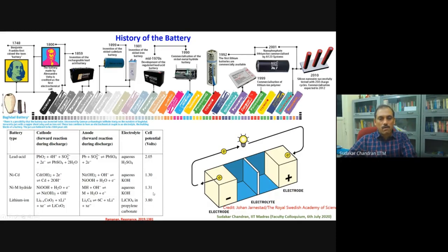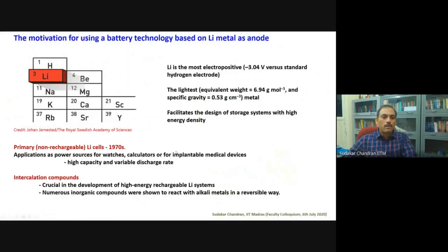But you can see a very contrasting difference. The voltage of the lithium ion batteries is almost 2 to 3 times more than any of the batteries known previously. Of course, the very use of lithium in the lithium ion battery came because it exhibits a very high capacity and also gives a very high discharge rate. This is possible because lithium is the most electropositive element we have. It's the very lightest one, and therefore it facilitates the design of storage systems with high energy density.